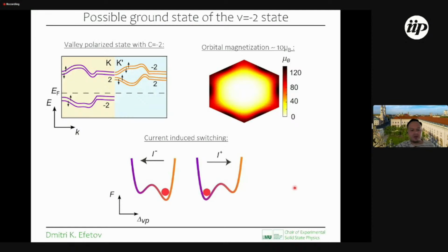process. And so one question, of course, we wanted to know is what type of magnetic state could produce such results. Without excluding any other state, one possible candidate in the process here would be a valley polarized state, where one valley is occupying two Chern bands, giving you a total Chern number of -2. And the other valley is completely unoccupied. With such a valley polarized state, one can calculate the Berry curvature winding numbers, and also the loop currents which are created in the states. And we find that there is an orbital magnetization of the state which is around 10 Bohr magnetons. So we can quantify the magnitude of this magnetic state.